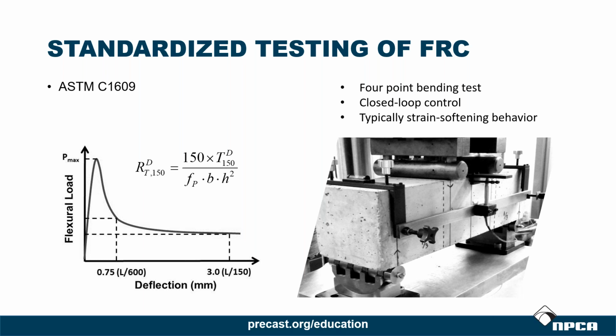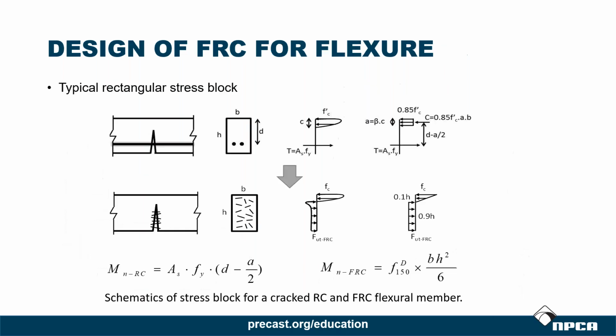This is a 4-point bending test run under very controlled, specific applications where we take concrete, we crack it open, and then we measure how fibers resist the load or prevent that concrete from cracking farther. Whether you have a slab on grade or a precast piece of concrete that's resisting earth pressure or has to do with water tightness, we can then find out what is the crack width we wish to evaluate that concrete under, or what is the loading that that concrete may be subjected to, and make sure that the fiber is providing the engineering performance that we need to resist.